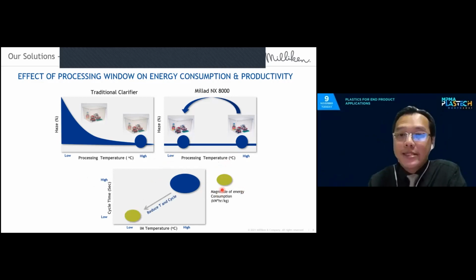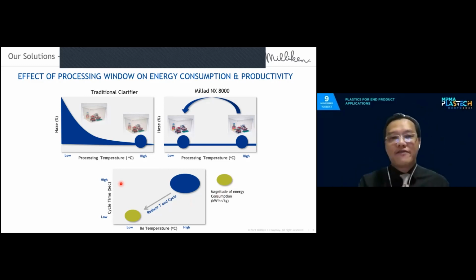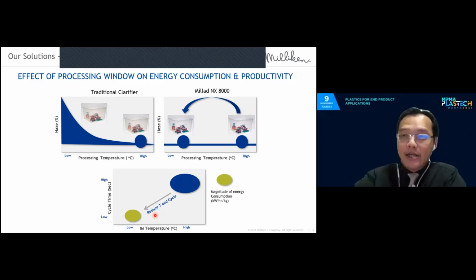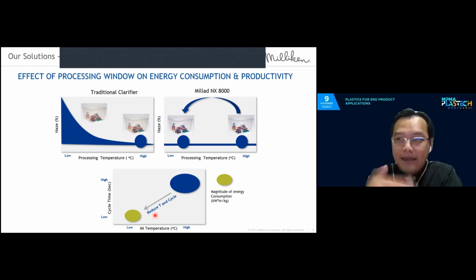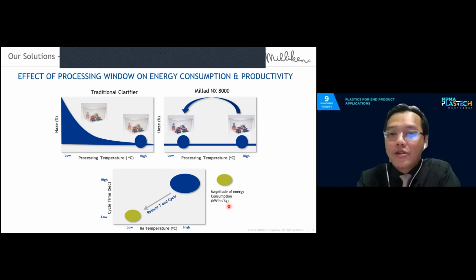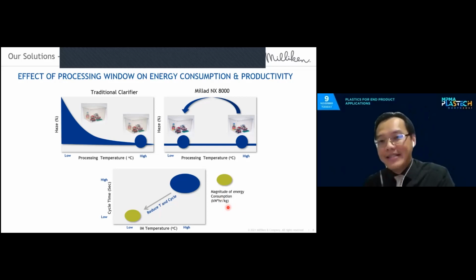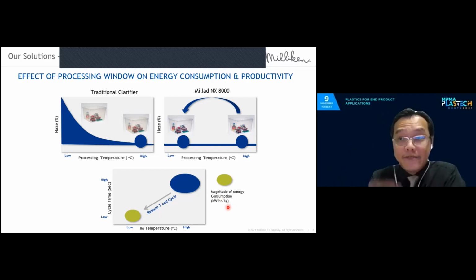So by reducing the temperature, because now we do not have the roadblock, right? We do not have the bottleneck of needing high temperatures for the clarifying agent to work properly. Most of the time, we can also reduce the cycle time, because again, you are injecting a cooler melt. You now need less cooling in the molding before you can eject properly. And therefore, you can reduce both energy needed for heating of your extruder, as well as improve productivity, right? Low cycle time, up to 10 to 15% productivity increase, which means that the energy needed to produce 1 kg or 1 part or 1 ton normalized will be even smaller. So productivity increase, faster outputs, more parts per machine, but also energy savings per part.